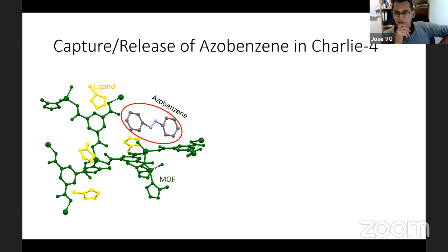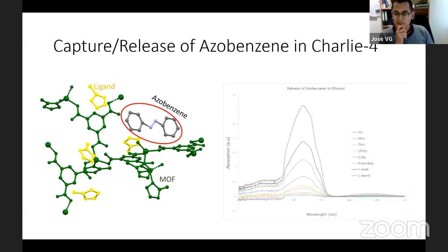This, of course, is not new, but that gives an application to this kind of MOF. So this is new to Charlie 4. What is surprising is that when we introduce this Charlie 4 loaded with azobenzene into ethanol, we can actually see some slow release of the azobenzene.